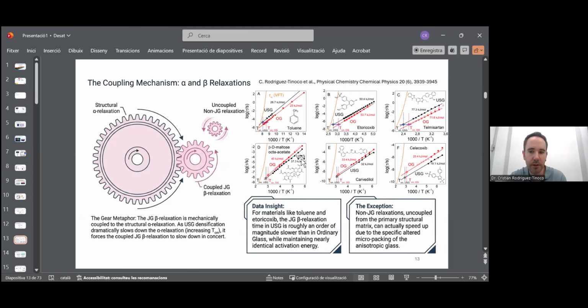On the other hand, we have other materials which exhibit another kind of relaxation, which is non-Johari-Goldstein, and in that case, what we see in the ultrastable state is that they are not slower, but they are faster, okay? So they are not linked with the structural relaxation of the system. This is a property of the Johari-Goldstein beta relaxation. So we can clearly distinguish which relaxations are Johari-Goldstein because they are linked with the alpha relaxation, and compare to those relaxations which are non-Johari-Goldstein, which are not linked with the alpha relaxation, okay? This is giving some extra information about the secondary relaxations, which is also a field of debate. There are other things that I could explain about that, but I will not go into much detail.